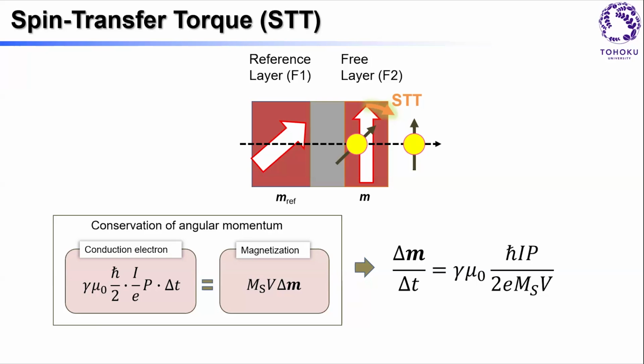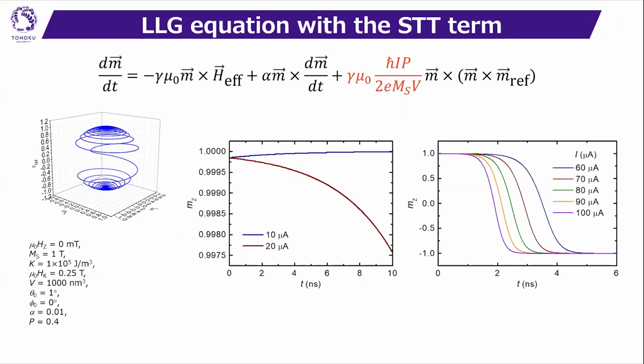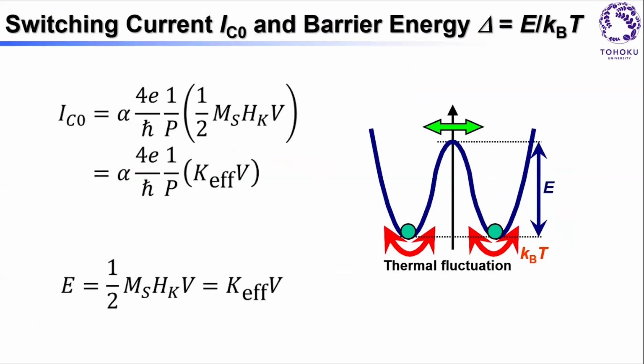Spin transfer torque, I again assume that you already know this. Basically, it induces precessional motion of magnetization, and above a certain threshold current, it switches from a north pole to a south pole in this case. Okay, so there's a threshold current, and this is a barrier that protects your bits from accidentally flipping by thermal fluctuation. So clearly, and intuitively, of course, when the barrier height is high, your memory is more stable, but you invest more current. And as you can see, there's an energy term, the same term in the simplest possible equation here. So these are all related.